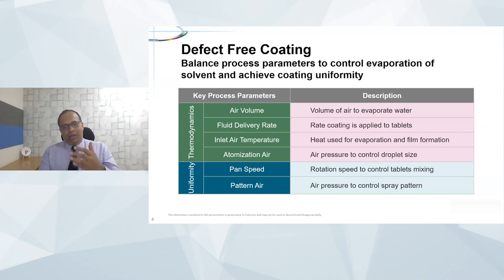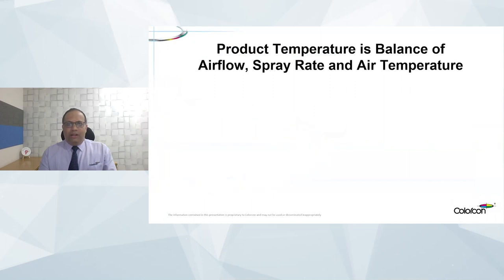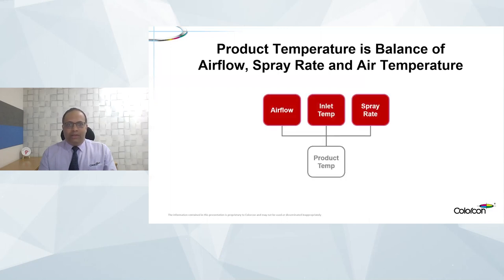When we say uniformity, how the tablets are getting distributed with respect to the pan speed, the baffles, as well as the distribution inside the pan when there is a multi-gun setup available. When we move to bigger scale machines, when there are 4 guns, 6 guns, and beyond, it is important to ensure that there is a uniformity of distribution of spray inside the coating process. So coming to the thermodynamics part first, what we look at, the majority of the time, is the temperature of the product which is getting coated. That product temperature is a balance of three aspects of the process: the airflow, the spray rate, and the inlet air temperature. So we will look at each one of them one by one.